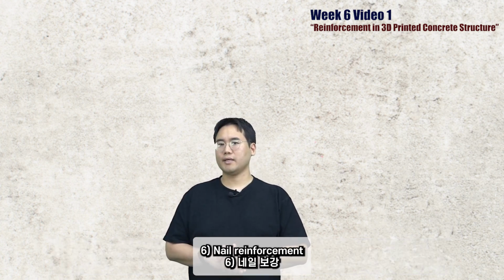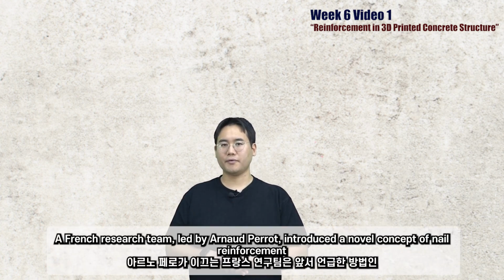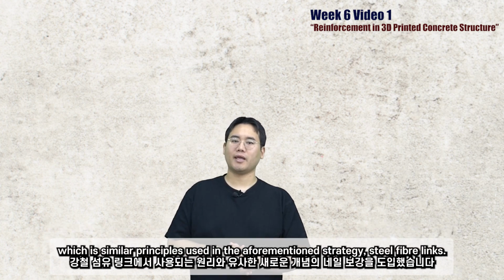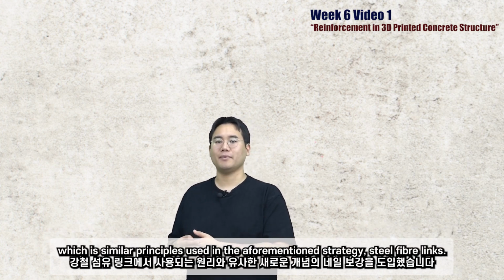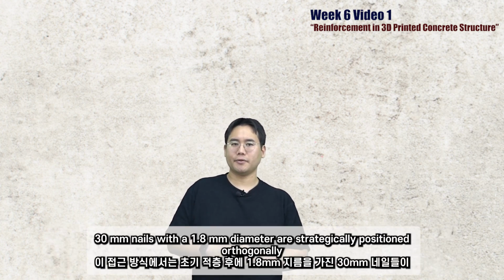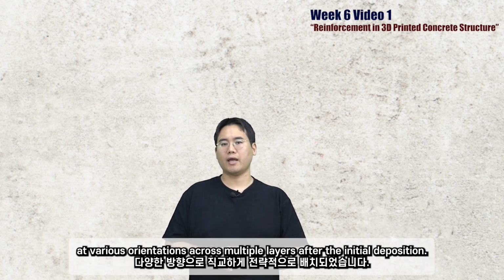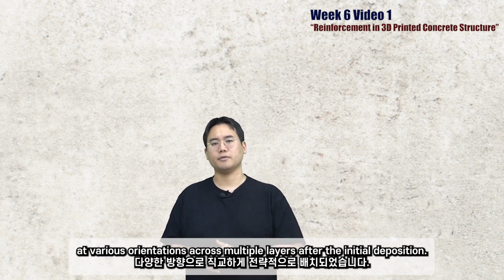The next one is called nail reinforcement. A French research team led by Professor Perrot introduces a novel concept of nail reinforcement, which is a similar principle used in the aforementioned strategy, steel fibre links. In this approach, 30 mm nails with a 1.8 mm diameter are strategically positioned orthogonally at various orientations across multiple layers after the initial deposition.